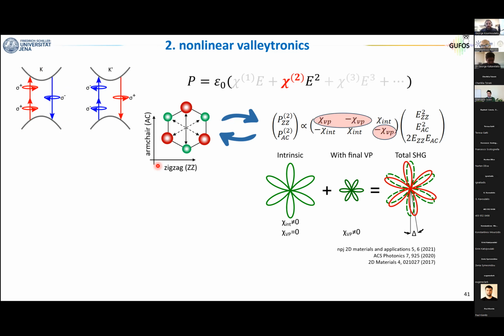Now you break time reversal symmetry, you reduce the symmetry of the system, you will have new terms in your nonlinear tensor that we call valley polarization terms. Now, from this matrix, you can immediately observe that these valley polarization terms are orthogonal with respect to the intrinsic response. In other words, now there is a new element or a new second harmonic that if you excite the sample along the armchair direction, you emit second harmonic along the zigzag. So orthogonal to the intrinsic response. Overall, this six-fold pattern will be rotated by a certain angle, delta or theta, and this angle is a direct fingerprint of valley imbalance and broken time reversal symmetry.